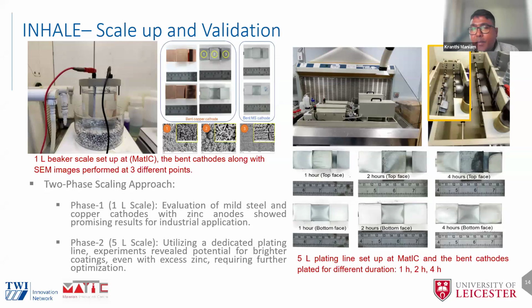And you can see the plating line which was set up as a part of this project. And you can see that we also could perform the 5 liters. Once we got good results with the 1 liter scale, I went on to scale up to a 5 liter scale, and I did it for a kind of throughput where I plated continuously for 1 hour, 2 hours, and 4 hours. And you can see the bottom images.